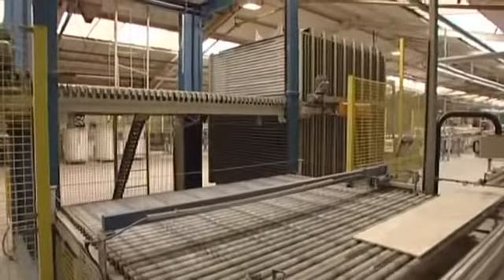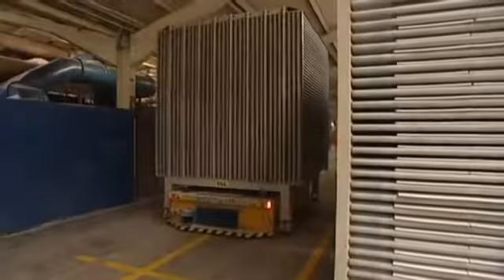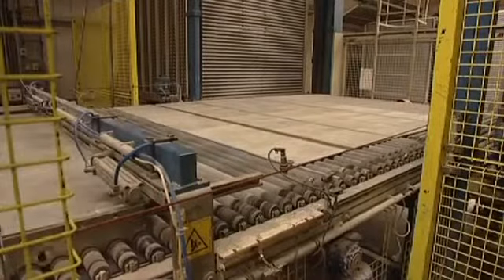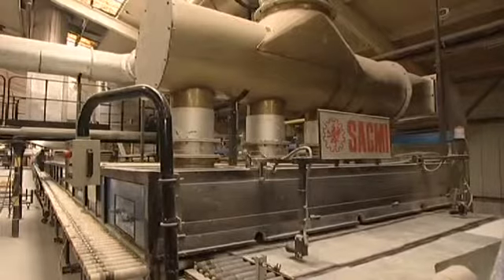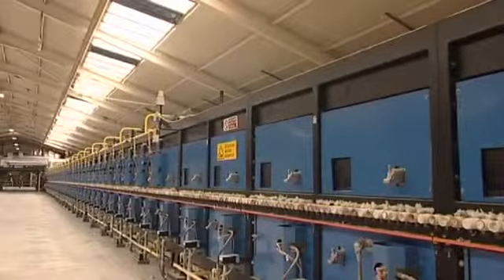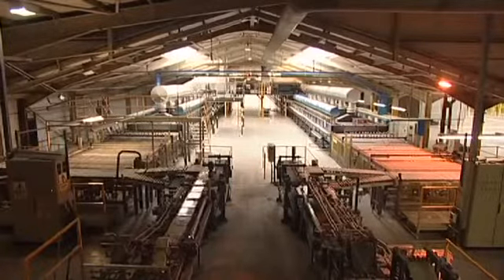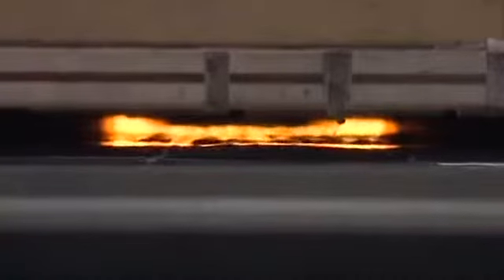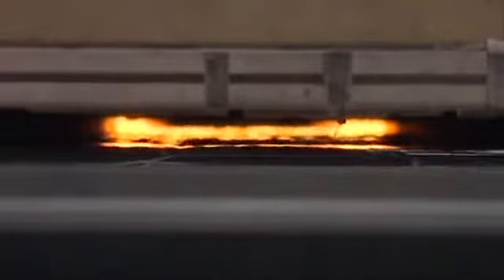After decorating, the tiles are sent to the kiln for firing. In this factory, this is done using computer-controlled wire-guided transporters, moving 200 square meters of tiles in special roller cages. The tiles are fed into the single-layer roller hearth kiln, which is over 100 meters long. Depending on the size of tile, the firing process can be as quick as 33 minutes, the largest tiles taking just under an hour. The tiles are gradually preheated before achieving the firing temperature of 1,130 degrees centigrade.